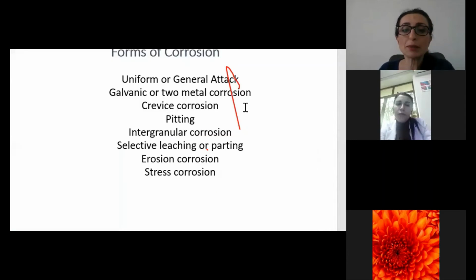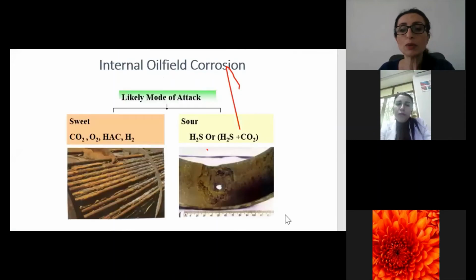As I told you, there are many types of corrosion, and uniform and localized corrosion have different forms. These include galvanic or two-metal corrosion, crevice corrosion, pitting, intergranular corrosion, selective leaching or parting, erosion corrosion, and stress corrosion. Also, in the oil field we face very frequently sweet and sour mediums, which affect the pH of the fluid and cause metal attack. If the dissolved gas is an acid gas, we call this sour. If it's other gases like CO2, oxygen, some hydrocarbons, and organic acids, we call these sweet gases.